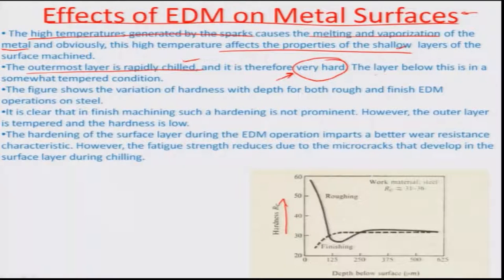Obviously, there is going to be a layer below this hard layer which is somewhat tempered in its condition. If I look at the profile in case of a roughing EDM operation, and by roughing we mean a very high spark energy, we can see how the hardness changes as a function of depth. On the surface the hardness is pretty high, in the range of about 60 Rockwell hardness, 60 HRC, and it goes down at a depth of about 125 microns below the surface, where the hardness really is an all time low, which is probably about 25 HRC. So, from 60 to 25 HRC.